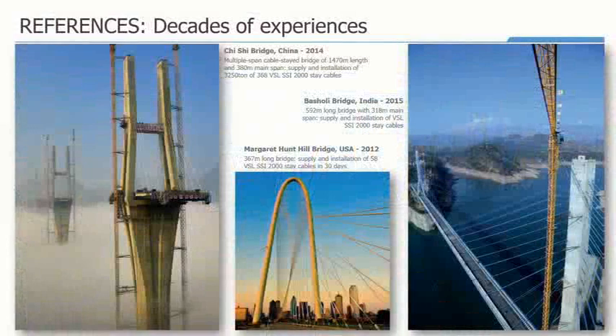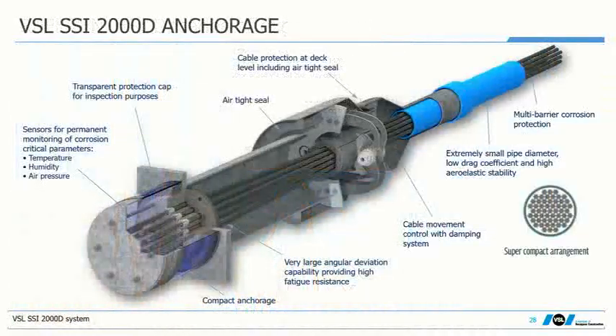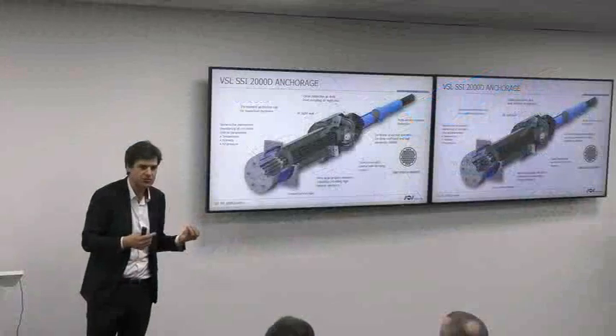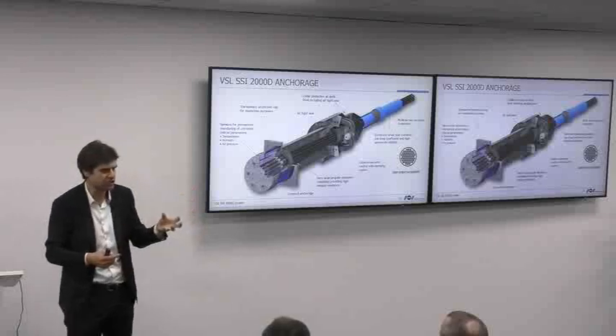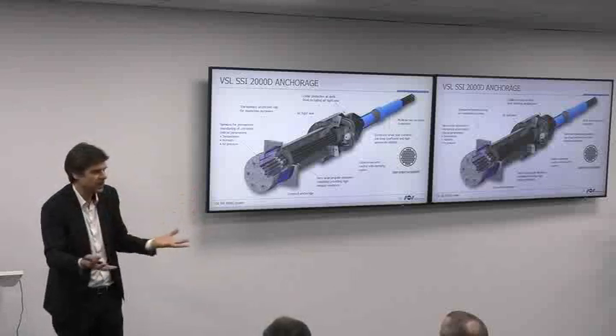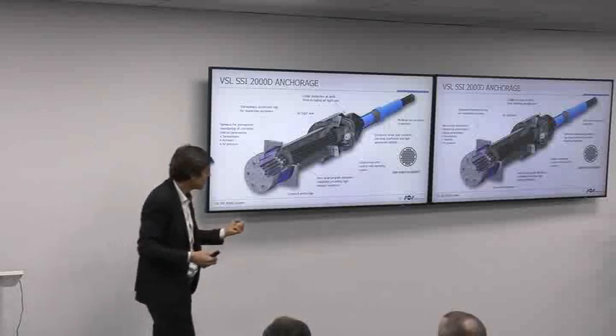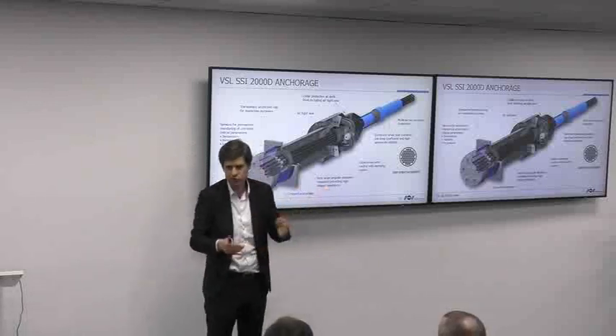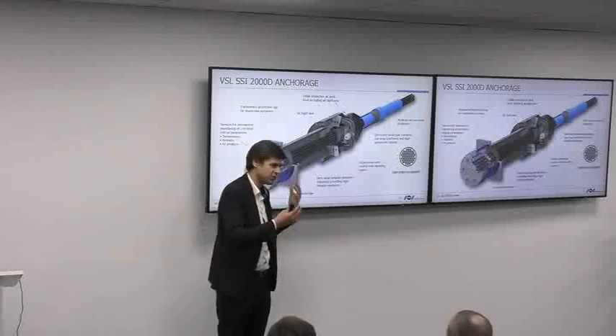So I just make a... This is a development that VSL started like 15 or 20 years ago. We call it the dehumidified system. We depart completely from the requirement we have today, or the recommendation, which calls for having strand with a wax injection, sheathing, a lot of petrol-based material inside. And we replace this passive corrosion protection with an active corrosion protection.